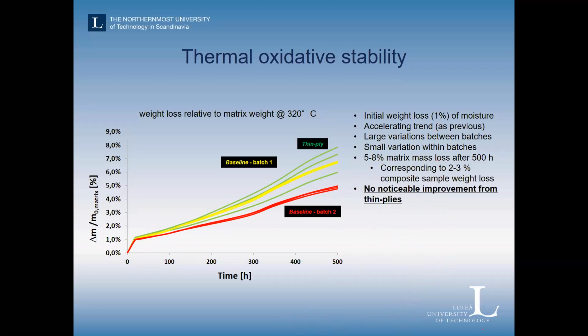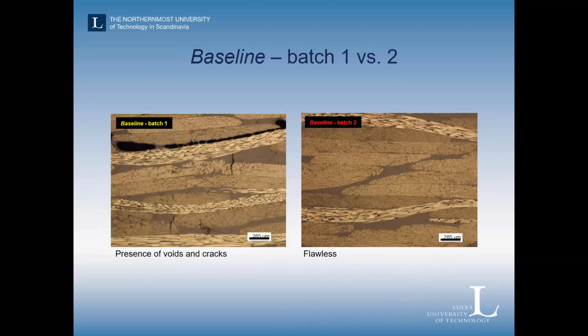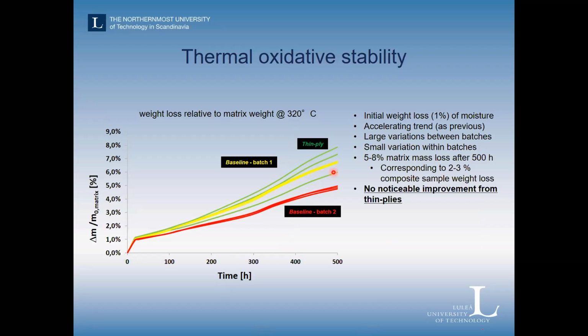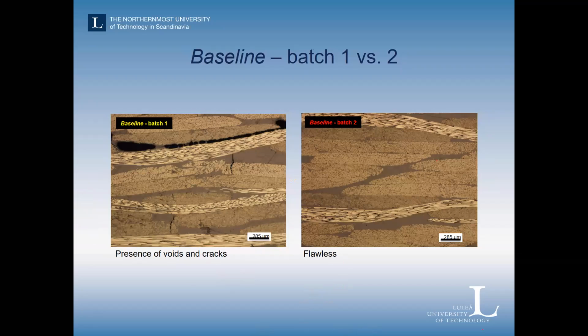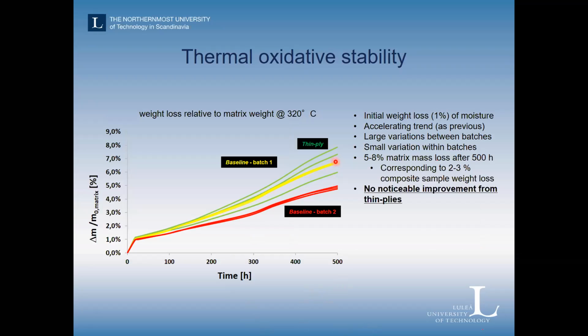One thing that we clearly observed is there's no noticeable improvement from the thin plies. And what seemed to be more important, if we go back and look at the red one and the yellow one, they are quite different. The big difference between the yellow one, the one that we lose quite a lot of weight in, and the red one is indicated here, and we see that the presence of initial voids and cracks in the first one was quite large when we looked at the microscopy images, whereas the baseline of the batch 2 was rather flawless. So this seemed to be one of the very important aspects, and we know that from previous work also, that these kinds of defects create paths for oxygen and degradation to occur.